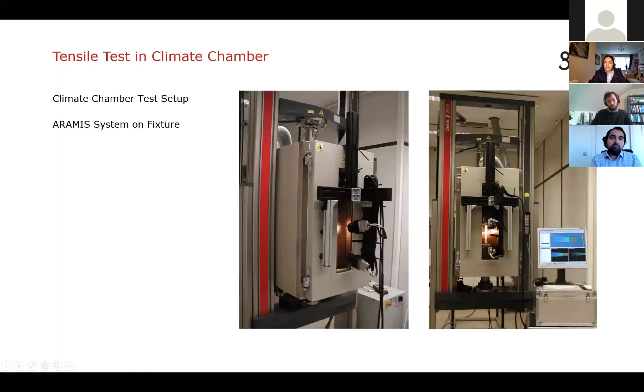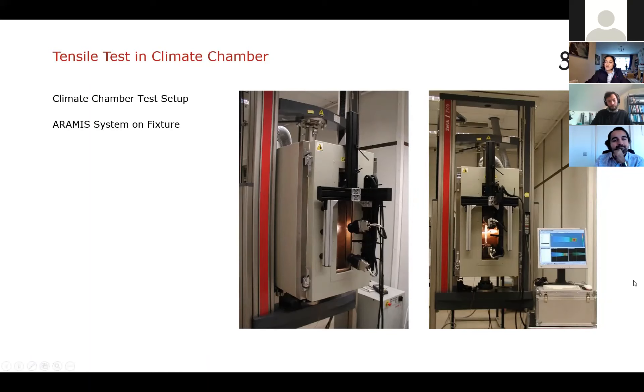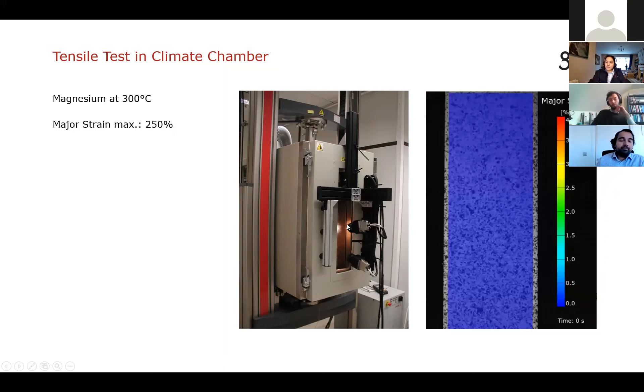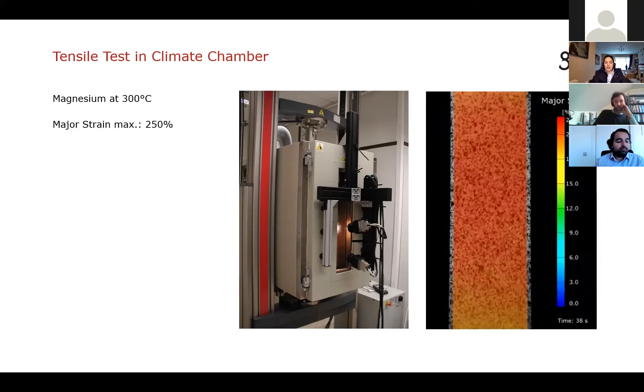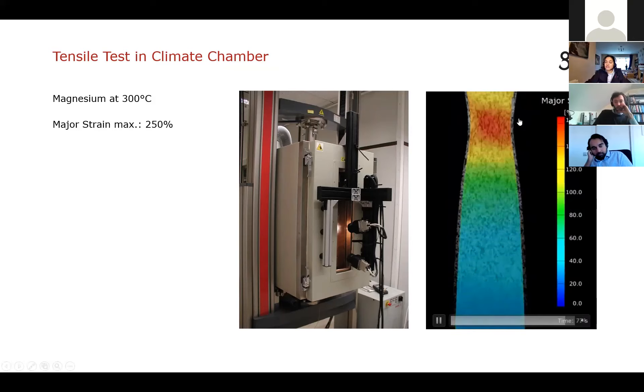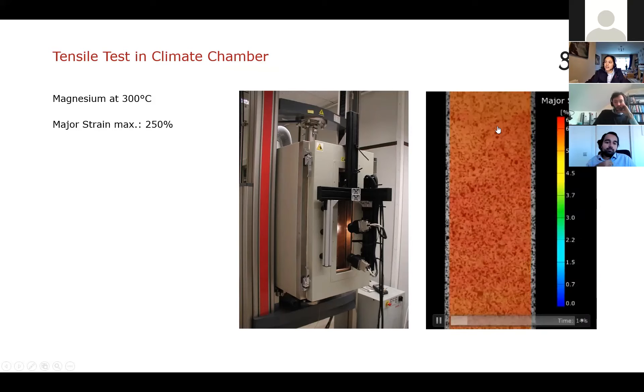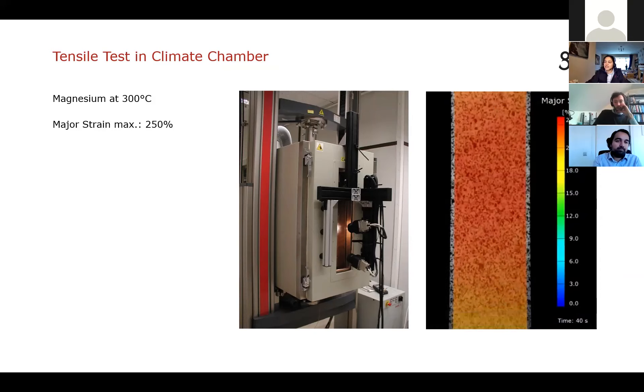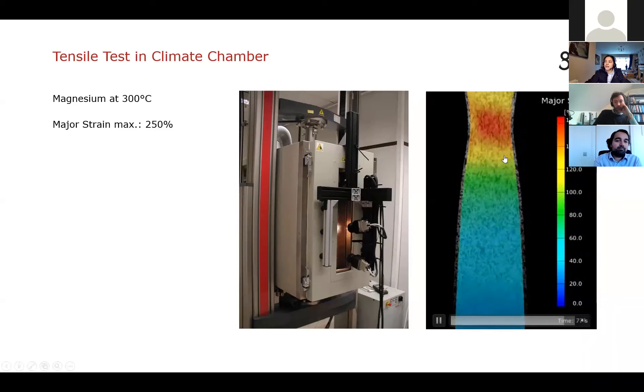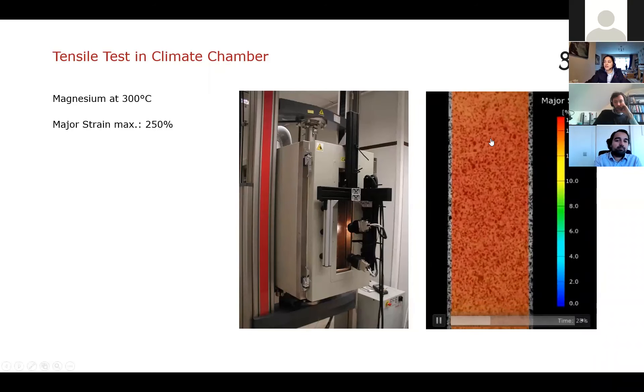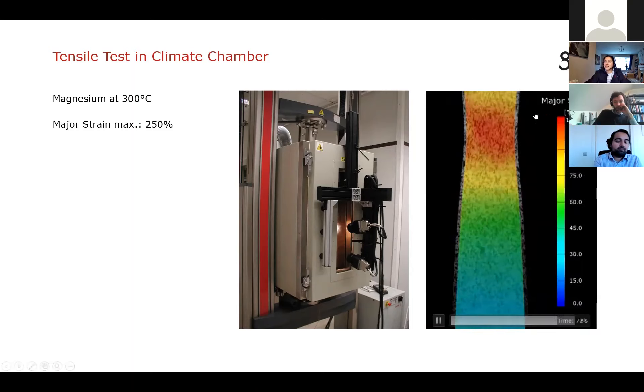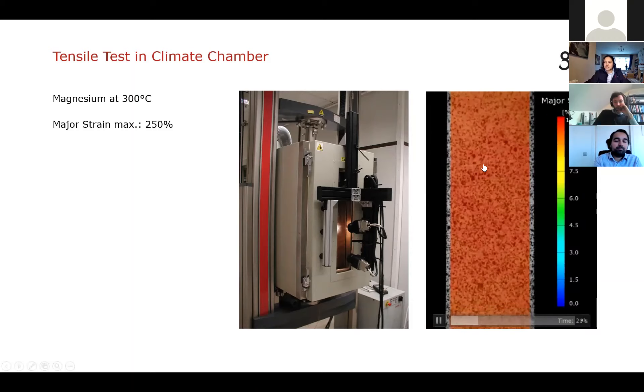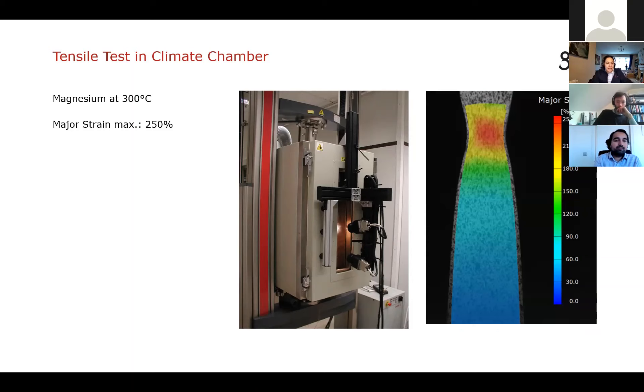So a couple of examples of this here. We've got a tensile test in a climate chamber. And this is quite an old example, to be honest, but it's a really good one because the customer, well, first they said that we could share the results, which is always nice. But also they attached the sensor to the door of the tensile test chamber. So it's always looking in at the sample. The part being measured is magnesium. It was measured at 300 degrees and it forms a very small neck. But it's very hard to predict where this neck is going to be. So using DIC, we can just do a full field measurement and then we can see where the necking occurs because we're looking at the whole sample. Of course, because of the level of necking and thinning, this isn't a 2D sample anymore. This is very much a 3D sample by the end of the test. And these are the results sort of in the final image before failure.